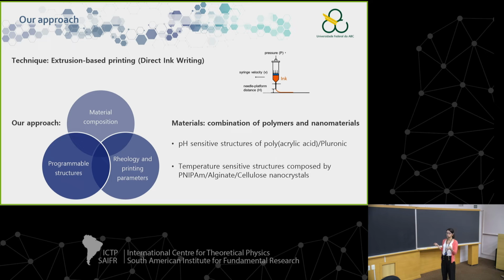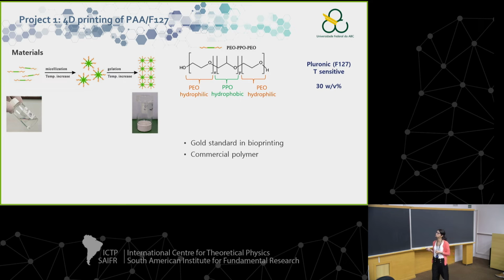And so the two projects I'm going to present are these. The first one is a pH-sensitive structure, and the other one a temperature-sensitive structure. In the first one, we use a mixture of polyacrylic acid, the polymer whose synthesis I showed, and Pluronic. Pluronic is a thermal-sensitive polymer that is widely used. It is the gold standard in bioprinting.